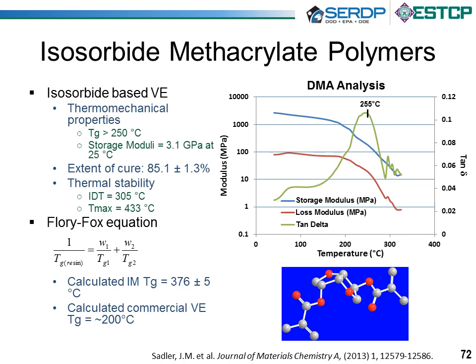Furthermore, we cured this resin, for the purposes of science, with styrene, because we felt we made a fairly defective network. When we cured it with styrene, we got about the same glass transition temperature, 250 degrees Celsius, which allows us to use the Flory-Fox equation to predict the ultimate glass transition temperature of this isosorbide methacrylate, which we predicted at 376 degrees Celsius. Which, again, is far higher than that of the commercial vinyl ester crosslinkers of about 200 degrees Celsius. So, again, excellent performance for this isosorbide methacrylate.